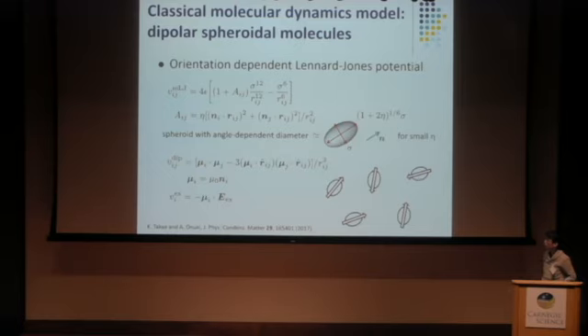This is our classical molecular model, and we slightly modify the Lennard-Jones pair interaction to include the particle shape anisotropy. The details are not important, but the important point is we can control the shape of the particle by one parameter, eta, in the second line. And we also take into account the electrostatic interactions. We proposed this model in this paper to study relaxor glassy behavior, but that is another story.